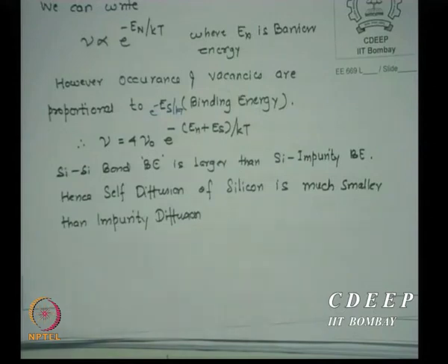This part is most important to show that substitutional impurity diffusion has a much lesser chance compared to the void ones, because there are enough voids, so many impurities can actually enter, which is very contrasting. People believe that impurities must first sit in a vacancy. No, first they are likely to sit in the voids, the interstitial sites, and then maybe move by seeing a vacancy around.